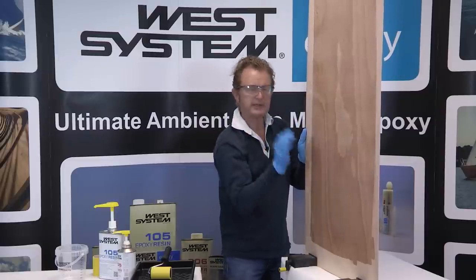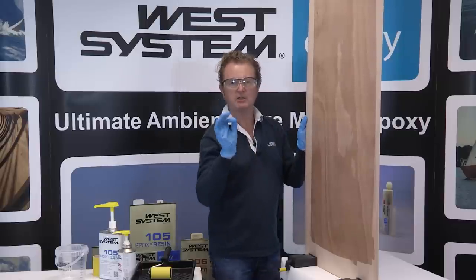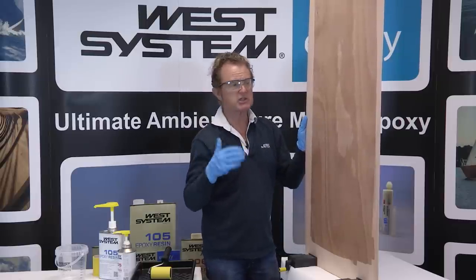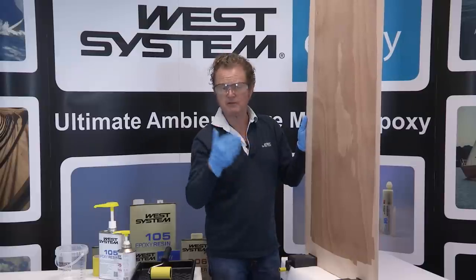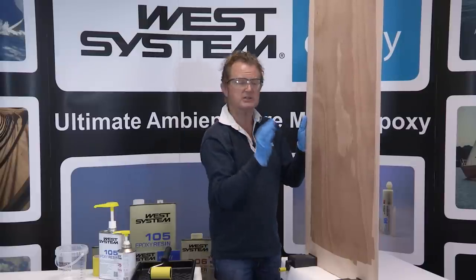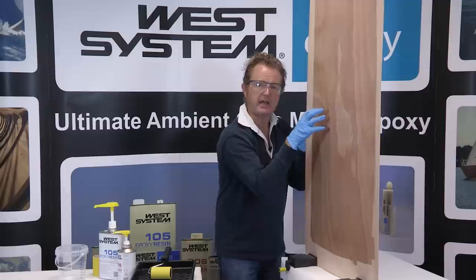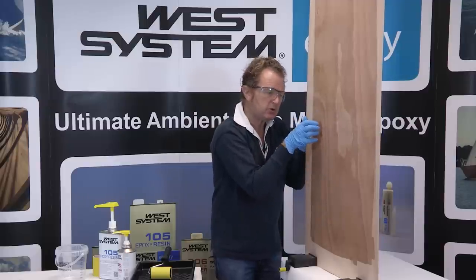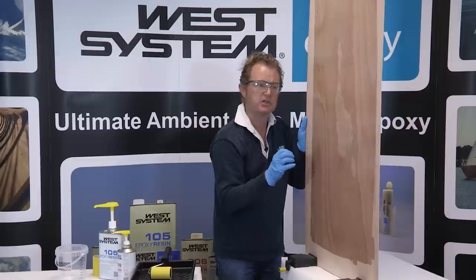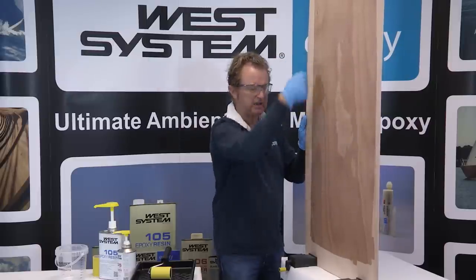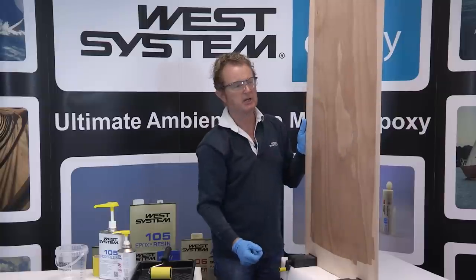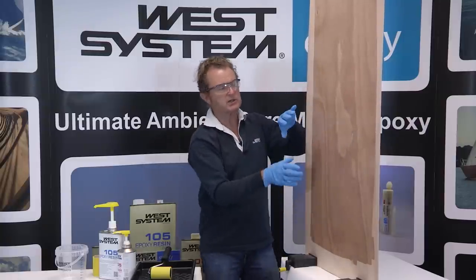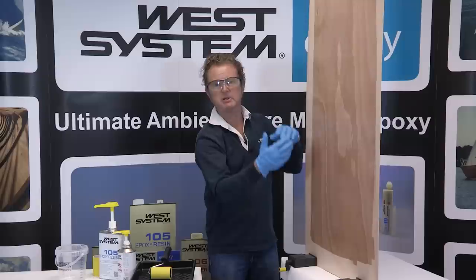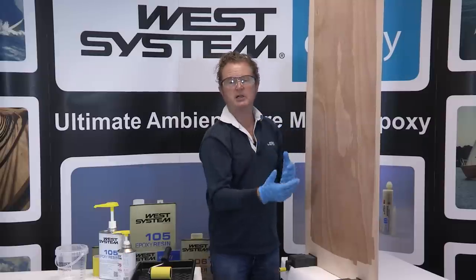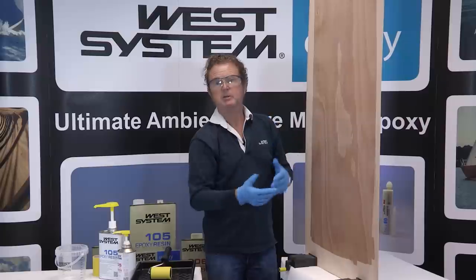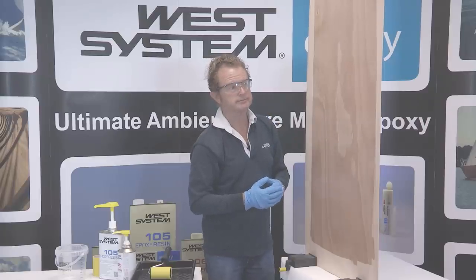Also, a thicker coating will cause a subtle exothermic reaction. That's to say that the coating will heat up very, very slightly. What that can do is expand the air within the wood fibre, and you can get air bubbles popping out of the surface. So it's very important to get a nice, thin, evenly distributed coat. Now I'm going to leave this for about 18 to 20 minutes just to become sticky, and then I'm going to add my glass fabric, and then I'll be wetting that out with more epoxy.